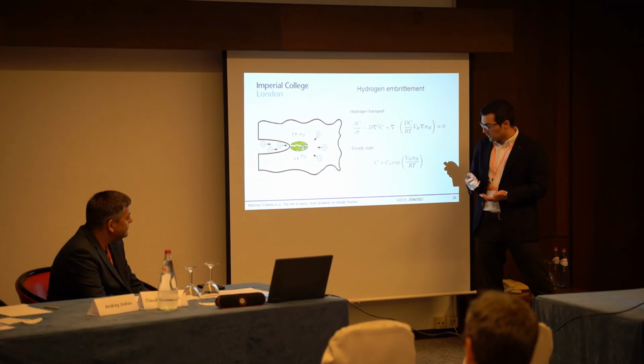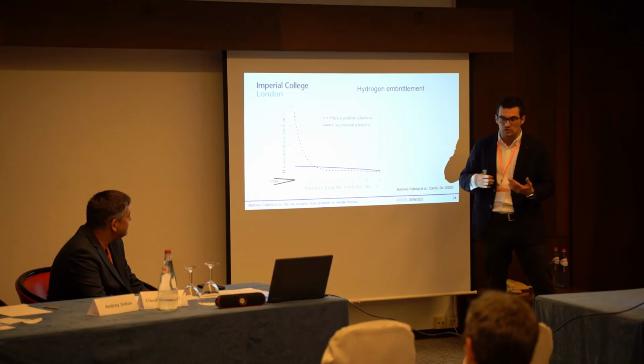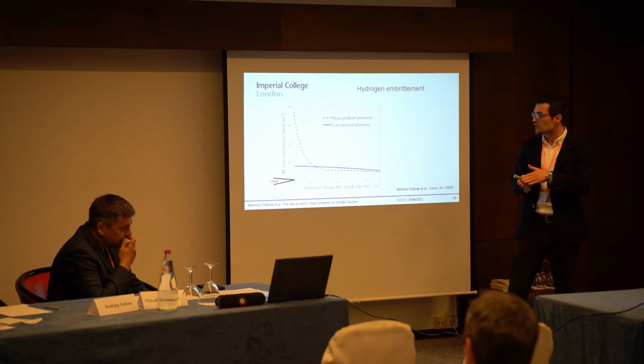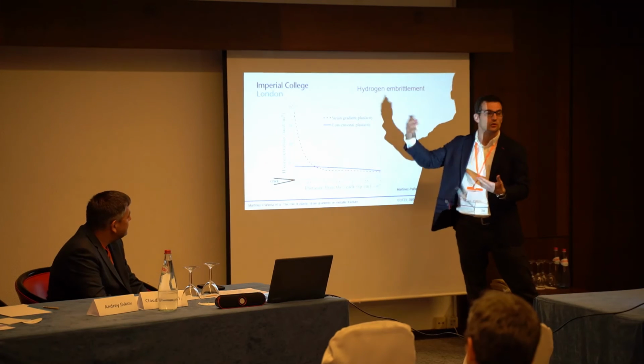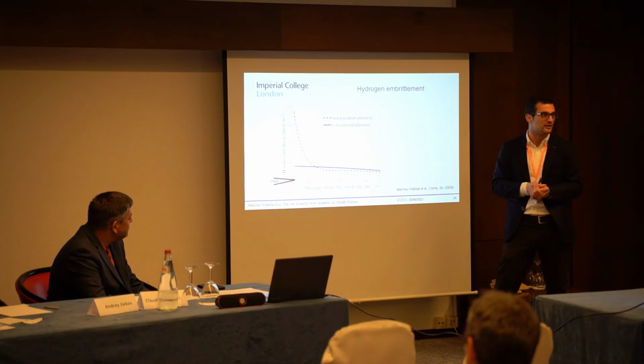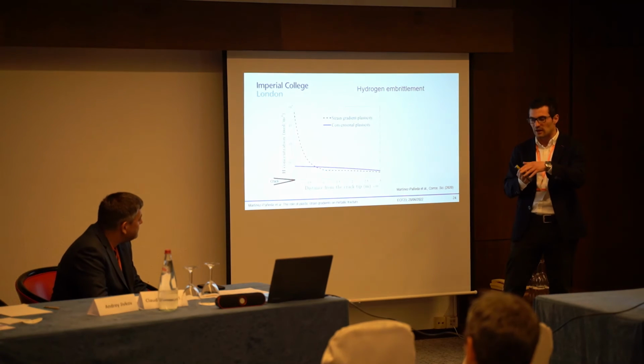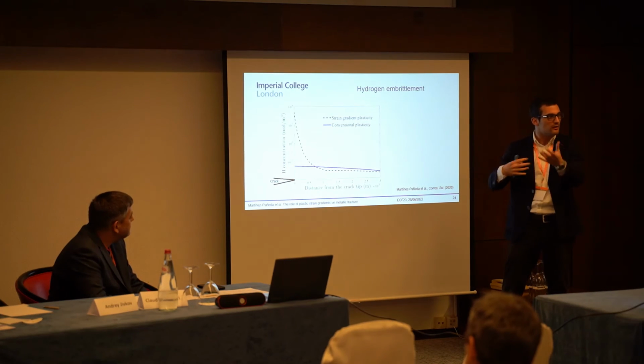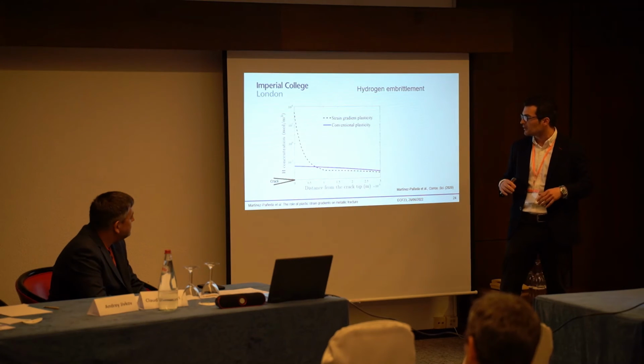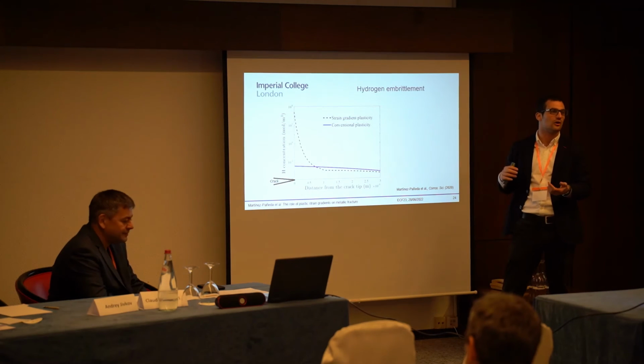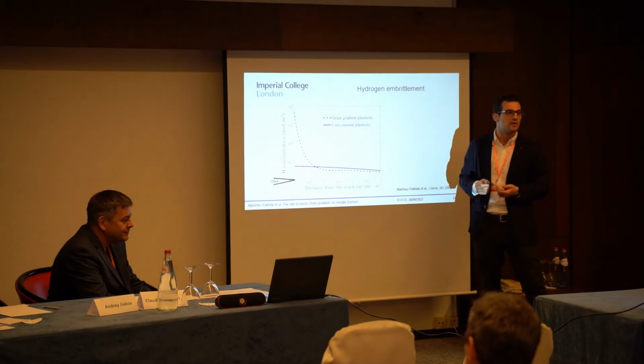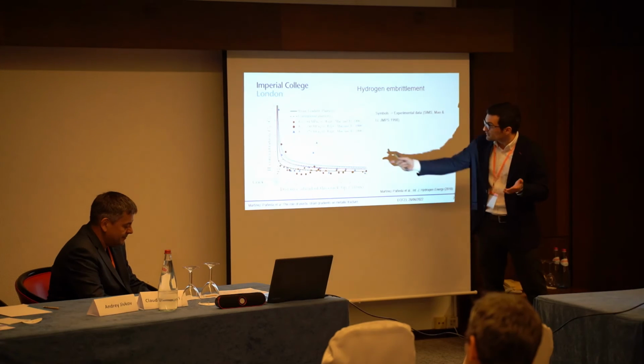So it is very important that you get your stresses right if you want to know what your hydrogen content is. And what we see here is that when you run these coupled deformation diffusion simulations, the hydrogen concentration that you get near your crack tip is much, much higher when you consider strain gradient plasticity. And it's difficult to measure experimentally how much hydrogen you have near your crack tip, but the few experimental measurements that have been out there seem to report much higher hydrogen contents than what you would expect using conventional plasticity theory.